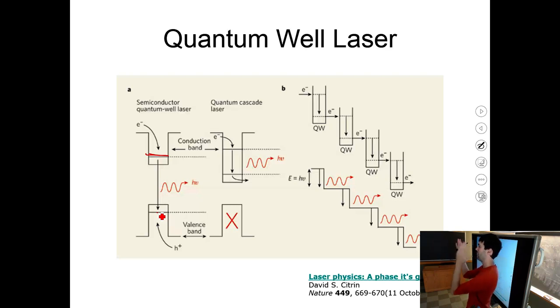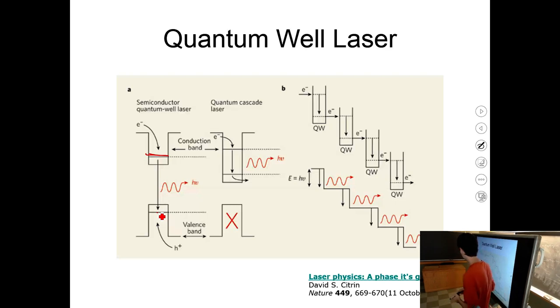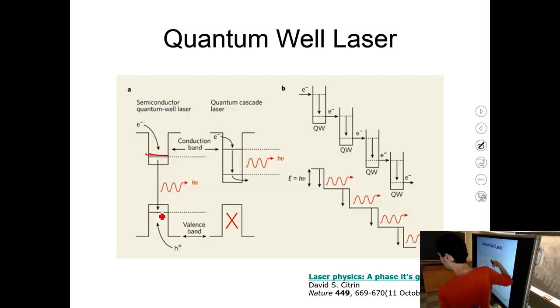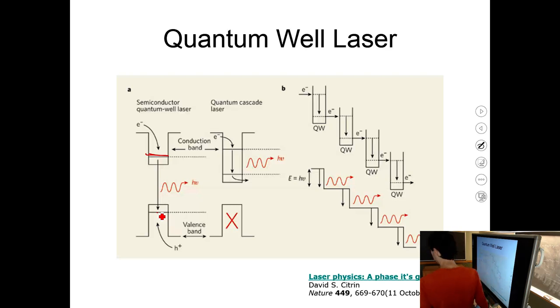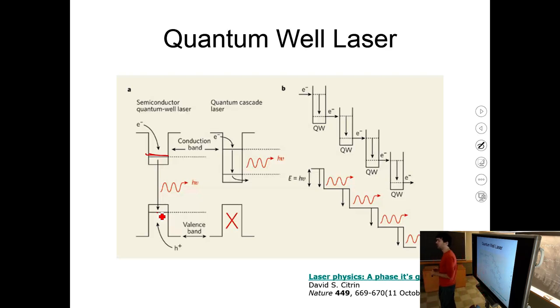You don't have to grow a single quantum well. You can make a sequence of quantum wells — alternating gallium arsenide and aluminum gallium arsenide — and bias them all with a voltage to line them up. This is called a quantum cascade: an electron falls to the next level several times, creating several photons along the way. The passage of a single electron creates multiple photons. Quantum cascade lasers are an actively developed technology.